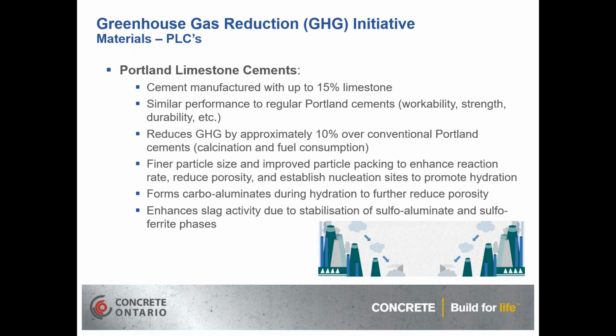And that is because we are diverting a portion of the limestone that would be used during the pyroprocessing, past the pyroprocessing stage, and incorporating it in the end with the milling. And by doing that, we all know that limestone is calcium carbonate. With the cement clinker, we're interested in the calcium oxide, which means we're going to flash off the carbon dioxide. So since we're taking 10% of that limestone and diverting it past that stage, incorporating it into the end, we're not releasing that 10% carbon dioxide, which would be from the calcination and the fuel consumption.